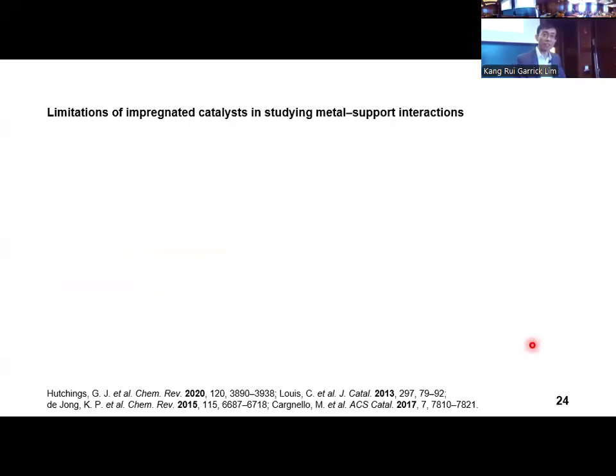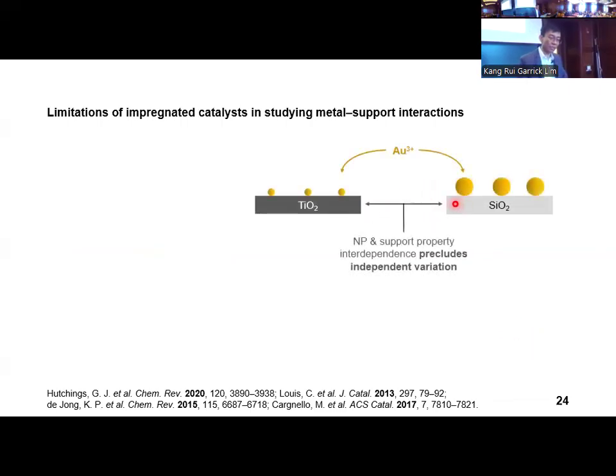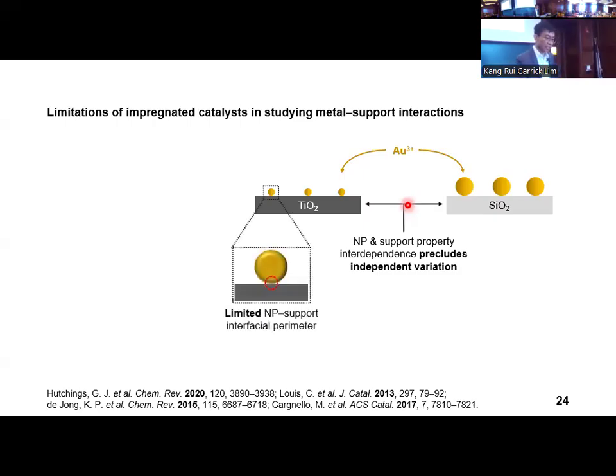However, the common impregnation method to prepare these catalysts is not best suited to investigate metal support interactions for three reasons. First, the support chemistry strongly influences the nanoparticle nucleation characteristics, which often results in different nanoparticle properties when nucleated on different supports. This strong interdependence of support and nanoparticle properties precludes independent variation to isolate effects arising solely from nanoparticle support interactions. Second, nucleating nanoparticles directly on the support surfaces limits our synthetic ability to tune the already limited nanoparticle support interfacial perimeter.